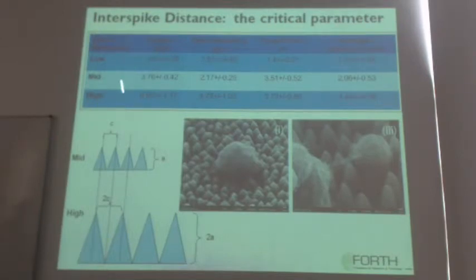Among the different morphological parameters that can influence or inhibit this cell differentiation, we have realized that the interspike distance is a critical parameter to tune cell differentiation. Here is a picture of a cell on low rough surfaces. You can see that the posts are not comparable to the dimension of the cell. However, in the high roughness surfaces, where cells are not differentiated, the size of the cells is comparable to the interspike area. So when the interspike area becomes comparable to the cell size, no differentiation is observed.